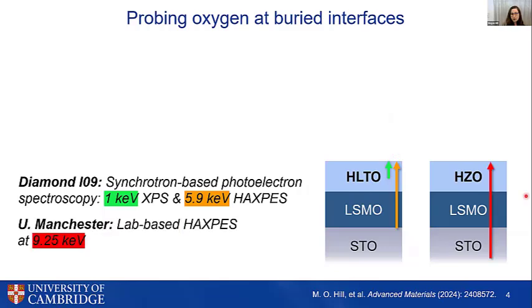We also used the lab-based HAXPES source at Manchester on the HZO film. And these 9.25 keV X-rays allowed us to probe all the way into the STO. And we also used angle-resolved HAXPES in order to probe different depths in our sample.